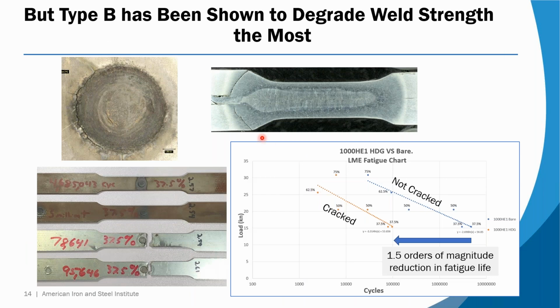Okay, type B is the main detriment in car body welding because this is what it looks like when you section through one of these. It can be extremely deep, could be full thickness of the sheet, and depending on the orientation, you can reduce the fatigue life up to 1.5 orders of magnitude.